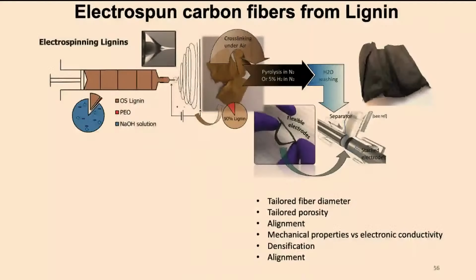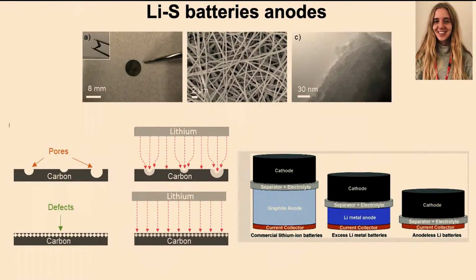Anyway, we can extract, well, we can't extract it. Jason can extract it, and Aggie. Then you can use this lignin to create these carbon fibers. You make a fiber using some electrospinning by applying some potential, as I said, like a spider web, and then you carbonize to get a freestanding carbon mat. And so that's our technology for making freestanding lithium-sulfur batteries.